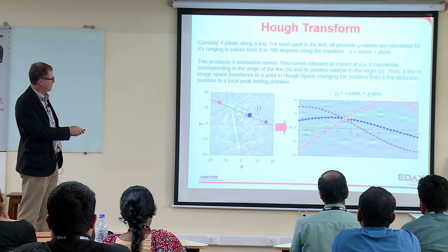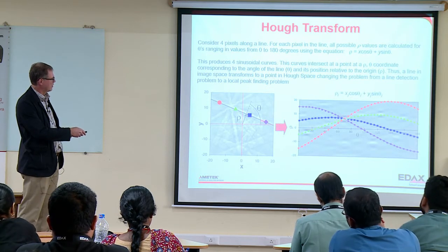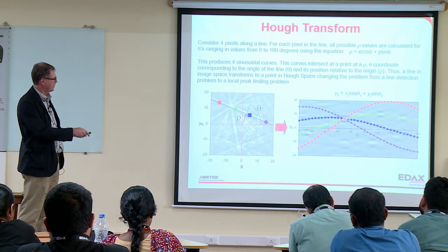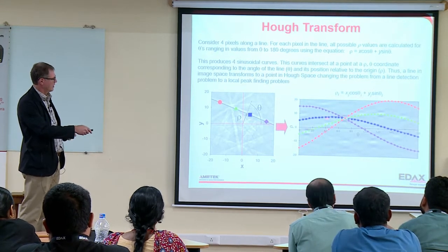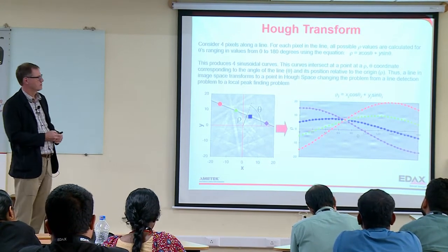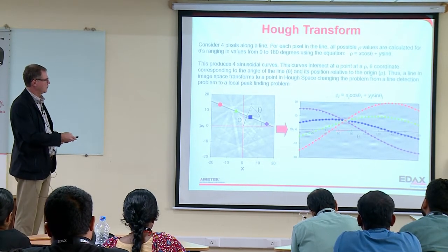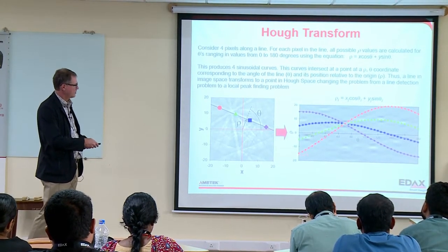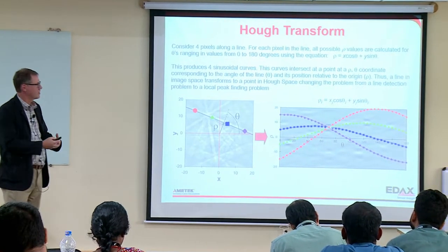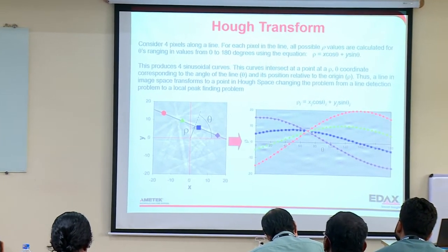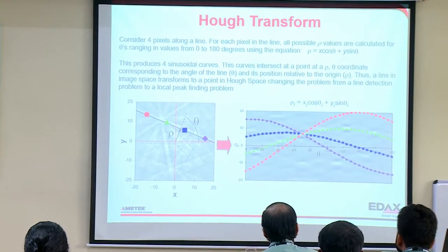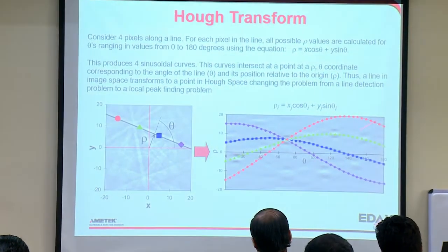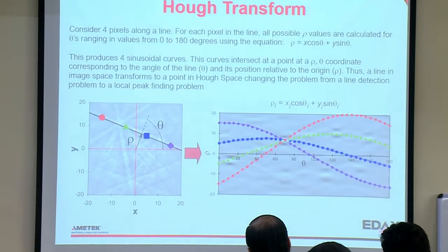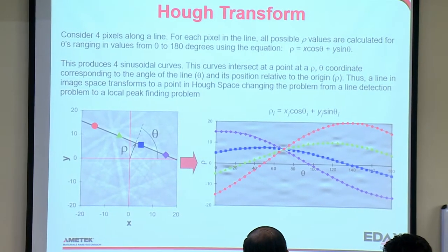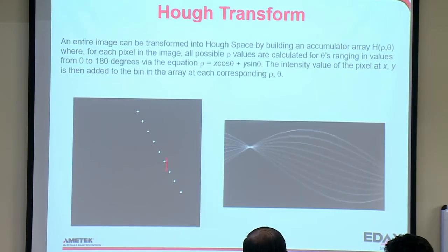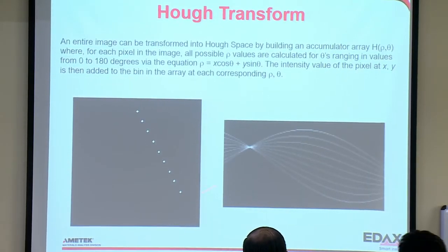If you have a set of pixels on a line like you show here, what you find is that the curve for each one of these pixels intersects at a point in the Hough space. The Hough transform is essentially an accumulator array. We're summing up the intensities of each pixel along these curved lines, and since those curves all intersect, you'll get a peak in Hough space there. So we've reduced the problem of finding this line to finding a peak.